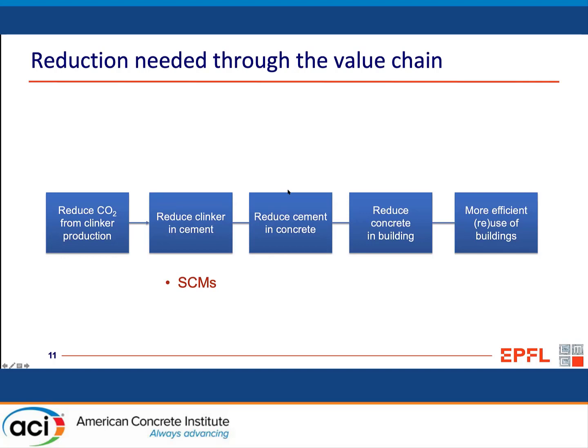But we shouldn't stop there, because we should look at the efficiency of the cement in the concrete. We can make very big savings there. And this can be as simple as having good aggregate grading. This can be as simple as using the admixtures which are available on the market, and as simple as using something like fillers in, say, self-compacting concrete rather than extra clinker.